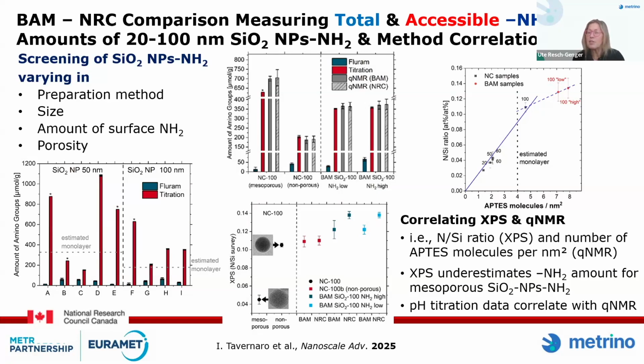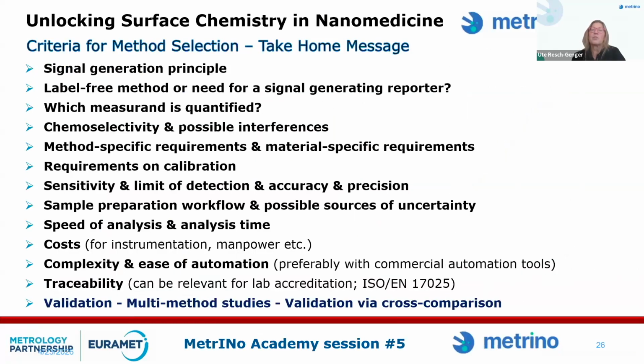But for XPS, you're limited with your penetration depths. So automatically you're supposed to find much less functional groups on the particle compared to qNMR in solution, for example. But this can also be used, for instance, for estimating monolayers on particles, getting an idea of surface morphology indirectly. So multi-method studies can help you to learn a lot about your particle. So what is the take-home message now?